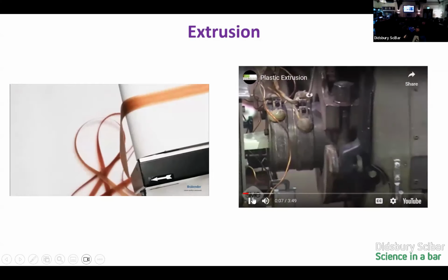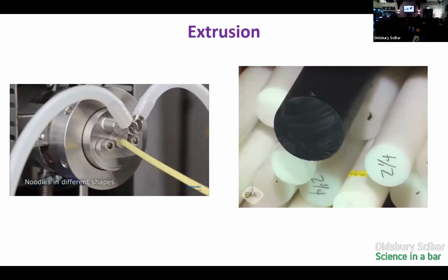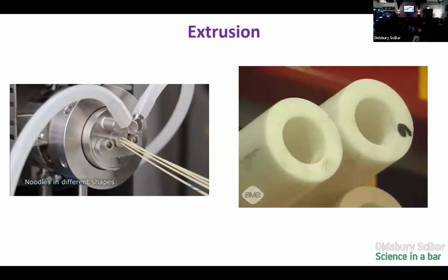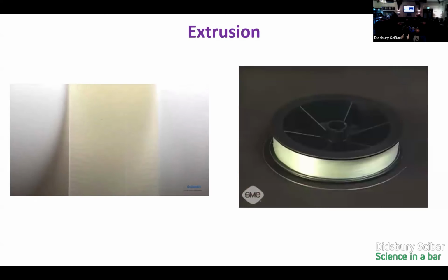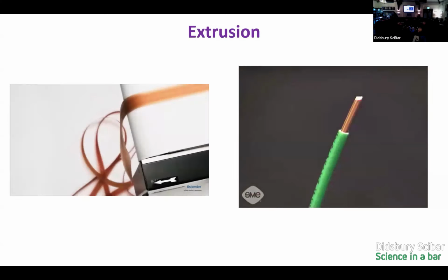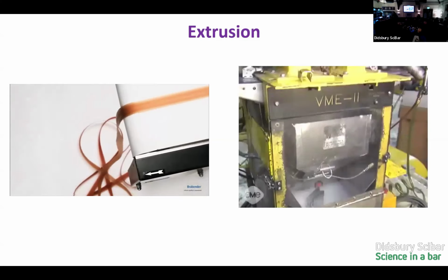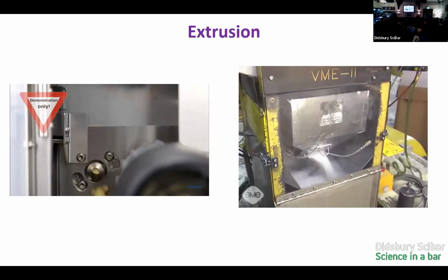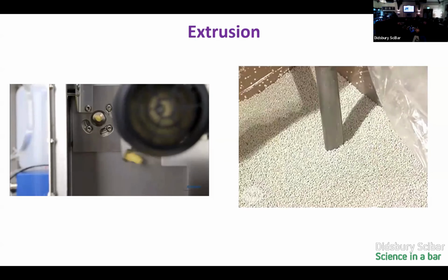Essentially, it's the same process, but effectively what we do is we heat up the polymer material so it's in its molten state. It's then forced through what's known as a die, or the small opening. And that can be various different shapes. So it can be these rod-like shapes. We can get pipes. We can get various different angles and shapes. So when the molten material is passed through the die, it's then cooled very rapidly and we get these solid materials. We can get flexible, essentially plates. We can get thin wires. We can get all kinds of different shapes. We can get wire coatings. And this is the process that loads and loads of polymer products are made using, okay?